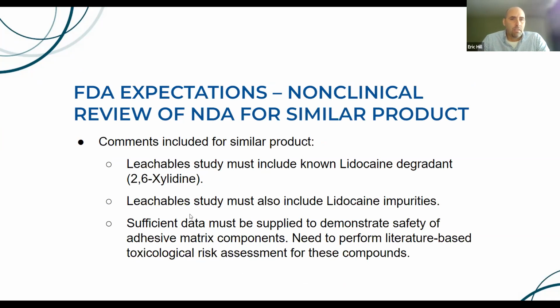They also directed specifically that the leachable study be able to target 2,6-xylidine. This is a lidocaine degradant. This was a little bit of a strange comment, honestly, from the FDA, because it's a degradant, and they were directing us to analyze for a known drug product degradant as part of a leachable study. Generally, a degradant would be analyzed as part of degradation testing, drug product degradation testing, or related compound testing, but they specifically mentioned that they wanted that to be included in the leachable study, so we did that. They also wanted to make sure the leachable study included any other lidocaine impurities. Again, a little bit outside the norm for an E&L study, but it was the FDA expectation, so we complied.